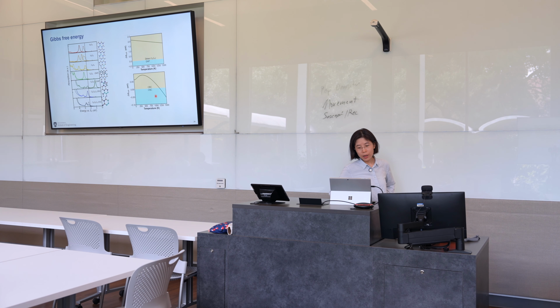So here I'm plotting the Gibbs free energy difference for two types of defects at different synthesis temperatures. This plot means if the Gibbs free energy difference is positive, dimer is preferred. Otherwise, DAP is preferred. The black curve is the actual calculated value. You can see these are all positive. That means dimer is more preferred than DAP.